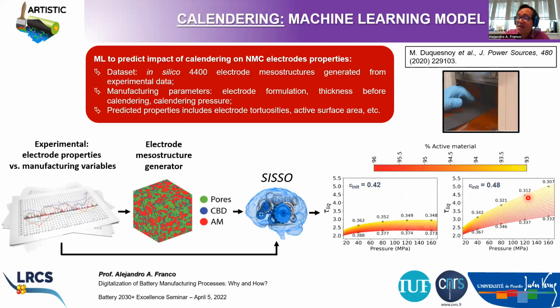You can also address the calendering process step using machine learning. And this is something that we published also a couple of years ago. And here, basically what we have done is we play at experimental level with electrode formulation, and we also measure the thickness of the electrode before the calendering process. We also play with the calendering pressure. And then we inject this experimental information into an electrode microstructure generator based on a stochastic algorithm. So basically this is a generator of 3D microstructures of electrodes, right? Where you can nicely locate in space active material particles, CBD, and pores.